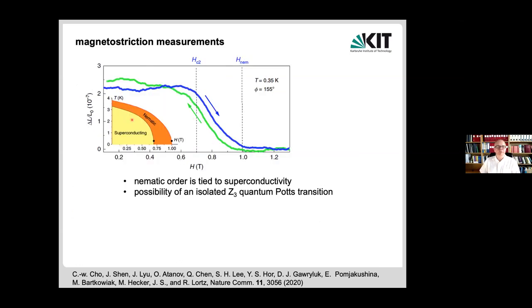Maybe a last experiment that you can look at is you can go to low temperatures and try to kill the superconducting state with a field. And then indeed, what you see is that the length changes recover. And so you go to the threefold symmetric state once you also go to a field that actually happens to be larger than the Hc2 fields that you can independently measure. And if this is to be taken seriously, it would mean that the splitting persists even at lowest temperature, and there would be an isolated Z3 quantum Potts transition in the system taking place here. Of course, again, this is a first order transition, at least for a clean sample.